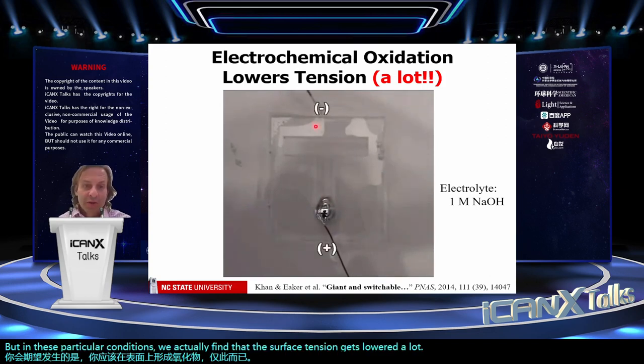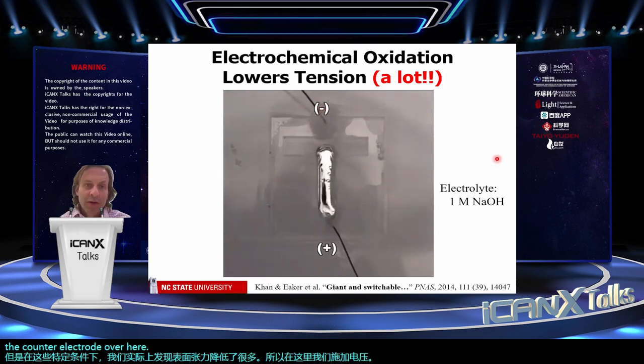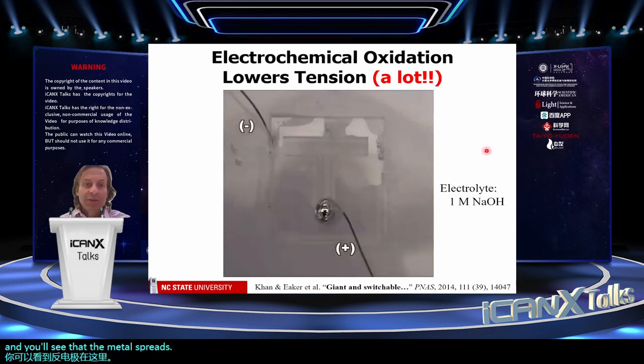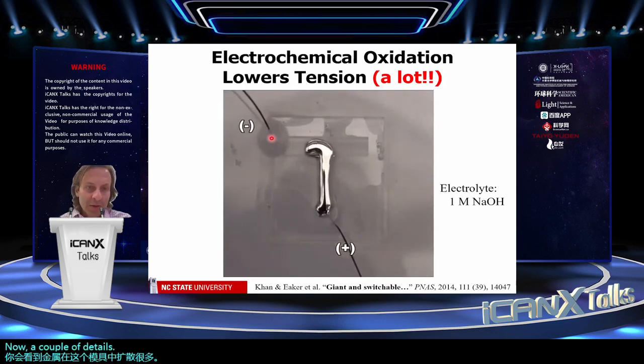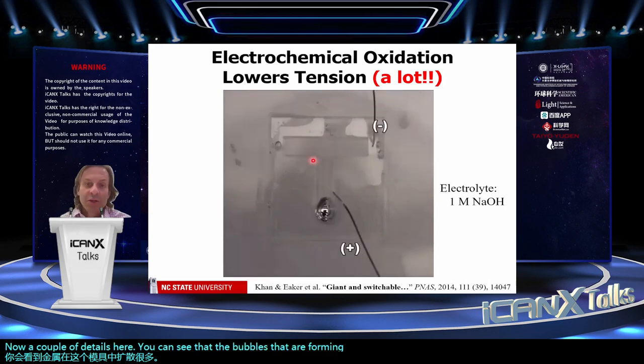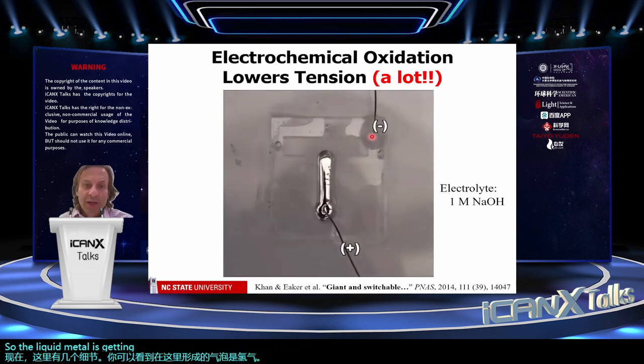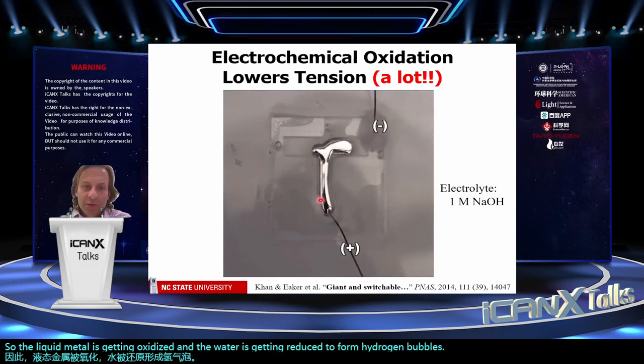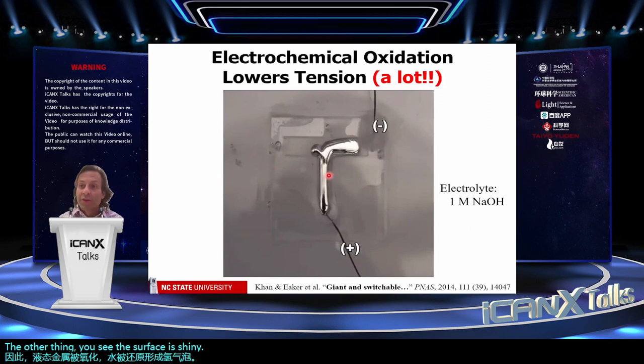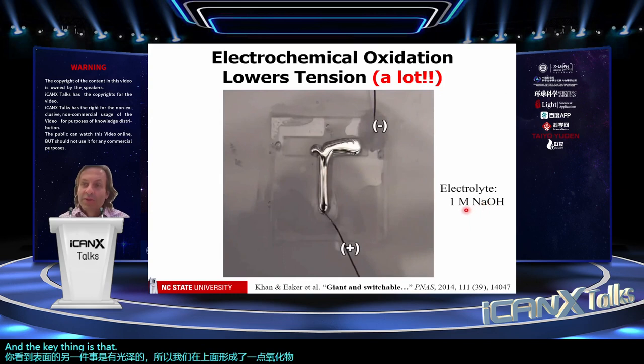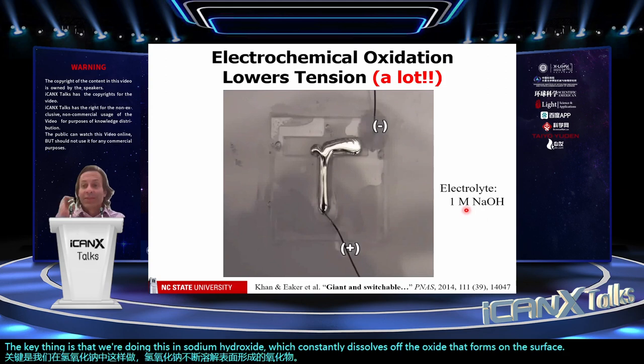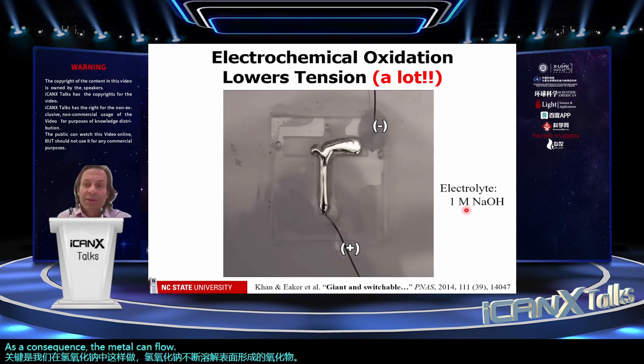So here we apply the voltage. You can see the counter electrode over here. And you'll see that the metal spreads a lot in this mold. Now, a couple of details here. You can see that the bubbles that are forming here, those are hydrogen. So the liquid metal is getting oxidized and the water is getting reduced to form hydrogen bubbles. The other thing, you see the surface is shiny, so we're forming a little bit of oxide on the surface, not much. And the key thing is that we're doing this in sodium hydroxide, which constantly dissolves off the oxide that forms on the surface. As a consequence, the metal can flow in these molds.